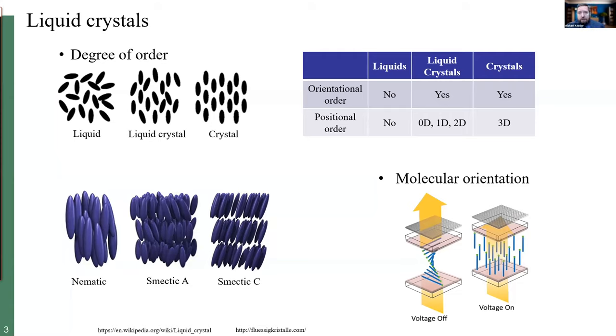There are different phases or types of liquid crystal. For example, a nematic crystal phase would have no positional order, but molecules self-align to have a long-range directional order. Or a smectic phase, where well-defined layers are formed and are positionally ordered along one direction. Liquid crystals are used ubiquitously in society today — for example, in liquid crystal displays — taking advantage of the ability to orient these mesogens using electric fields, magnetic fields, and other mechanisms.